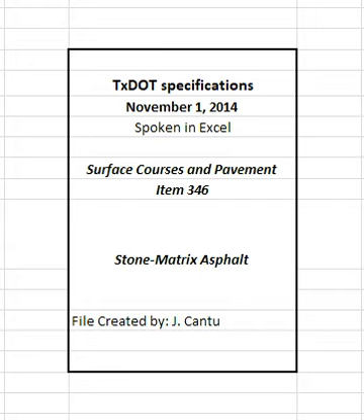Core samples, if taken, will be obtained from the center of the finished mat or other areas excluding the vehicle wheel paths. The engineer may require up to the entire sublot of any mixture failing the Hamburg wheel test to be removed and replaced at the contractor's expense. If the department's or department-approved laboratory's Hamburg wheel test results in a remove and replace condition, the contractor may request that the department confirm the results by retesting the failing material. The construction division will perform the Hamburg wheel tests and determine the final disposition of the material in question based on the department's test results.